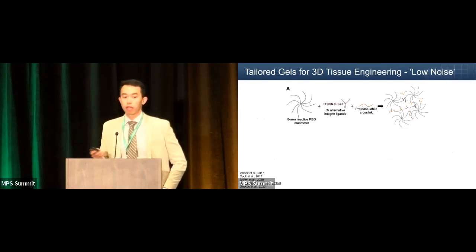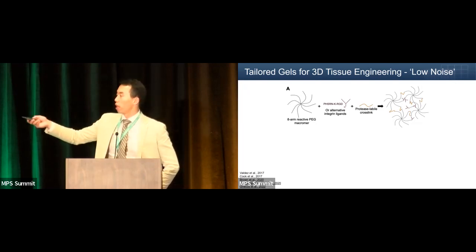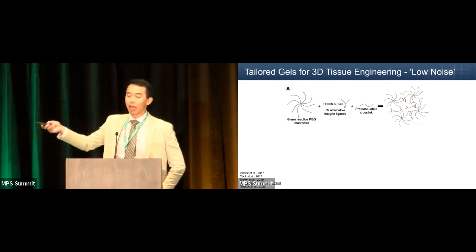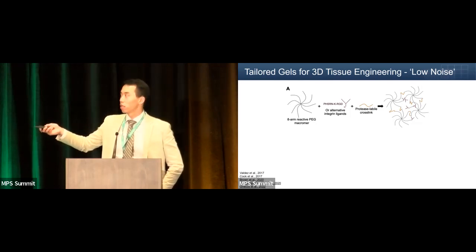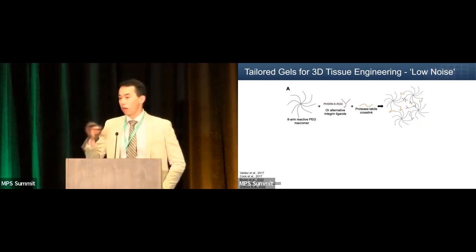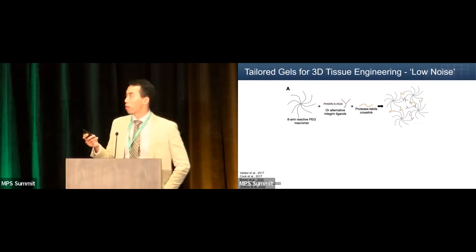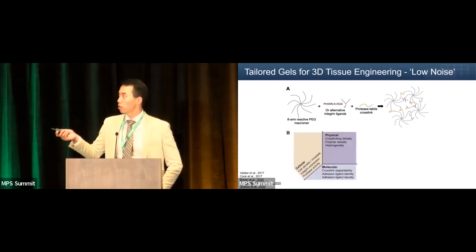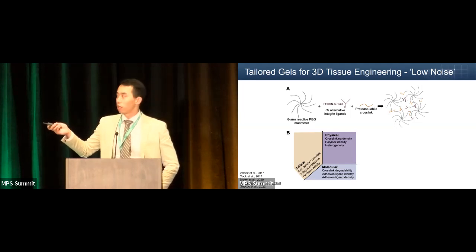So in the Griffith lab, we utilize a PEG-based hydrogel, which is based on an 8-arm reactive PEG macromer functionalized with a vinyl sulfone group, where we can add binders such as synthetic RGD or GFOGER, which mimic collagen and fibronectin, and basement membrane binders that replicate collagen-4, laminin, and fibronectin, and generate these hydrogels, which are very reproducible and which are also MMP cleavable.